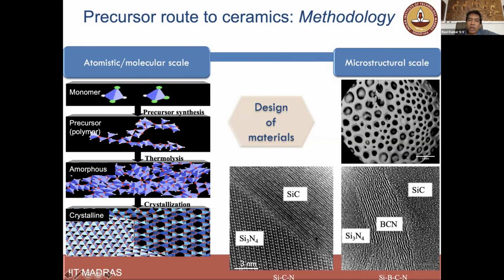I show this quite often because this kind of micrograph typically tells us what can be used for high temperature applications. The one which you see on the left-hand side, where you see silicon nitride and silicon carbide, you see that these two crystals are in direct contact, so the grain boundary is clean. On the other hand, I show you another microstructure on the right-hand side, where you have silicon carbide and silicon nitride with a sandwiched phase, which is a boron carbon nitrogen phase, which is again a design requirement to protect silicon nitride when you go to extremely high temperatures.